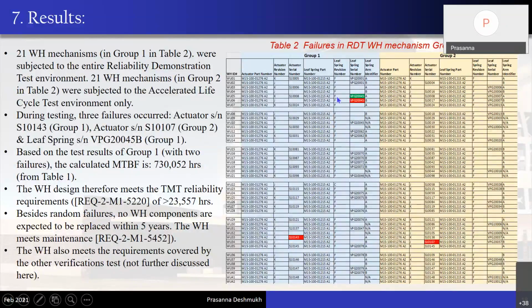And if we consider the worst case also, in a set of 21 actuators, 2 actuators failing, which corresponds to an MTBF of 730,000 hours, whereas our TMT requirement for operation is more than 23,000 hours of life from a given actuator. So which proves that this particular mechanism is way more reliable than what we need, and also it meets the requirements.